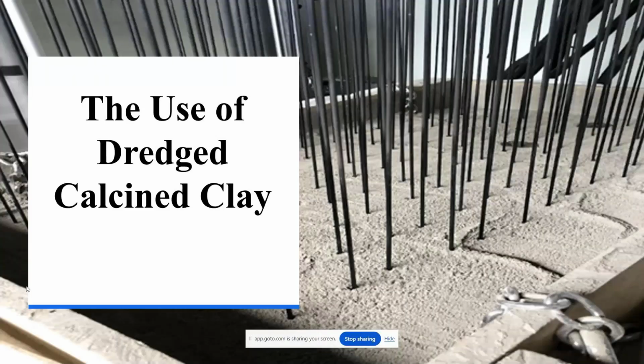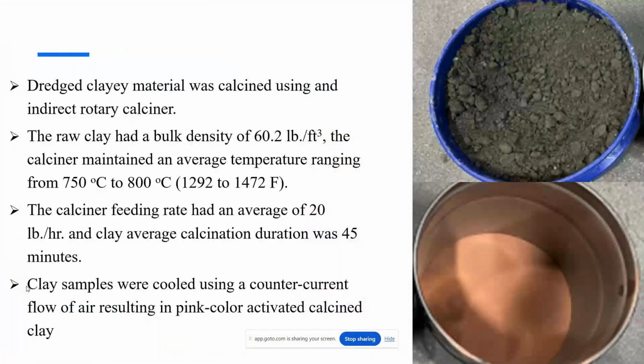So we started using calcined clay, or calcination of clay dredged from our own water beds. So on the right side, the top picture, this is dredged clay material that was obtained from a waterway in the state of Virginia, and it was transported to North Carolina. And then the lower side here, that is the picture of a calcined clay. It was calcinated in an indirect rotary calciner at a temperature of 750 to 800 degrees Celsius, which is anywhere from 1300 to 1500 Fahrenheit. And then the rate of calcination, or feeding the calciner, was 20 pounds of the material per hour, and the duration was 45 minutes for